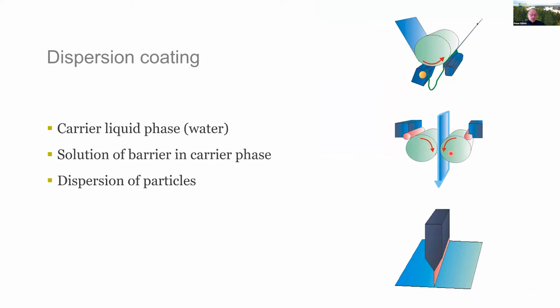What you can also do is put it in a water-carried phase, and make a dispersion or solution in water with the barrier material. This is something you can do with polyvinyl alcohol, as an example. Starch or cellulose is also possible, or hemicellulose. Then you apply it in a regular coater, whether it's a blade coater, a metering size press, or a curtain coater. All these are a little bit tricky, each in its own way.